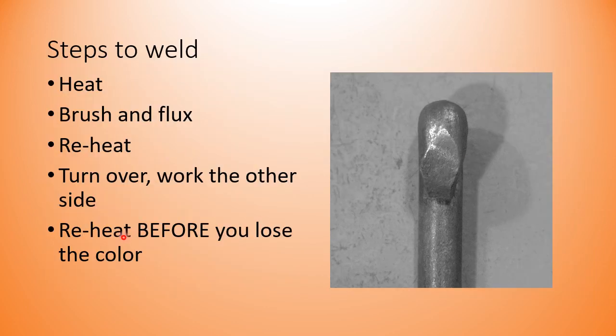Here are the steps to weld. The metal must be clean to weld. To obtain a clean surface, you're going to want to brush and flux your piece, as the flux is a corrosive that will dissolve the scale that forms while you're heating the piece. That scale will interfere with the weld. It also applies a protective coating to prevent more scale from forming.